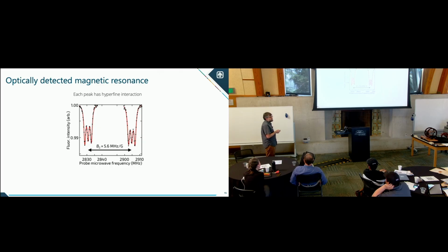The hyperfine interaction shows up in these optically detected magnetic resonance spectra because the most abundant nitrogen that you actually get is nitrogen-14, which also has a spin of 1. So this is a spin of minus 1, 0, and 1 from the nitrogen-14. And then you have the electron transitions on either side. This is actually a much better spectrum than I showed you before, with less power broadening. We can actually see this on the microscope over there when we do our demonstration.